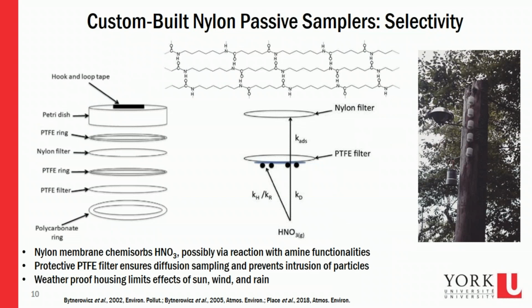And if you want to be able to sample that quantitatively, way downwind from sources like continental sources in Toronto, the way that you would go about it passively is with a selective material. What we want to do in this case, go to the literature, find out what's been done before. Turns out nylon actually has really great selectivity for sampling nitric acid. This is a polyamide polymer. The amine functional groups on this, we think, nobody's ever shown the mechanism, actually controls the uptake of nitric acid. So you're getting essentially ammonium nitrate forming on the surface, and it's a quantitative collection for nitric acid on that